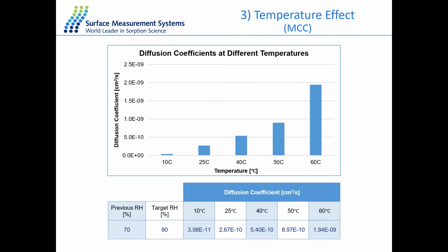And then we also calculated the diffusion constant for the water molecules at different temperatures. The diffusion is calculated with an average particle size for the microcrystalline cellulose material of 50 micrometers. And this diffusion constant also shows a trend of increasing with increasing temperature.